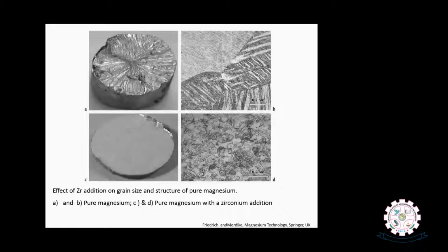based alloys. So when we see the first two figures, the top two figures, which are free from zirconium, even with the naked eye you can visibly observe the long elongated columnar grains. Whereas when we add zirconium to the pure magnesium, as shown in figures C and D, grain size was significantly decreased. So based on these observations, we can say there is a significant effect of zirconium on refining the magnesium microstructure. So this is one criterion by which magnesium alloys are classified.